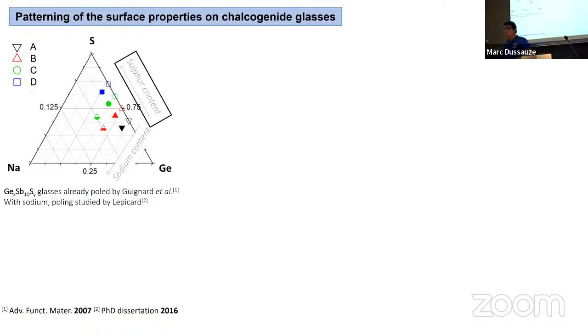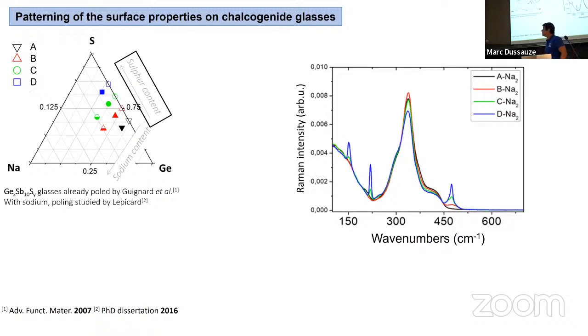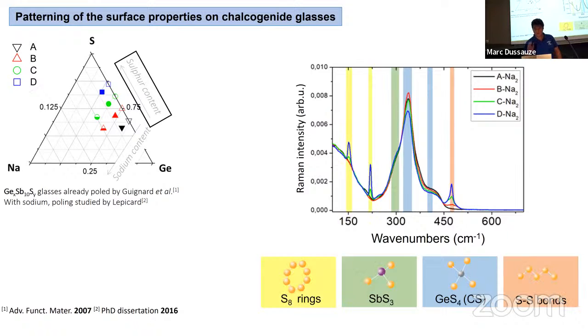Okay, the first thing we do, because we are glass chemists, we want to know the glass structure. So it's very important for us to know very well the materials that we are making. So for that, we do Raman spectroscopy, for example, where you have here the different kinds of structural units which form the glass structure. So you have the tetrahedral germanate units, where am I? Here, and the antimony units here, which are either connected by just a sulfur bridge or by sulfur rings, sulfur chains as a function of the sulfur content, of course.